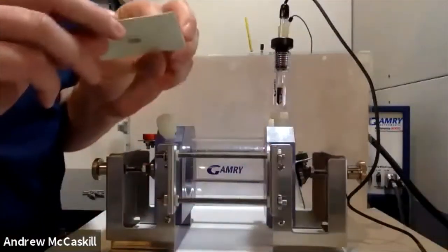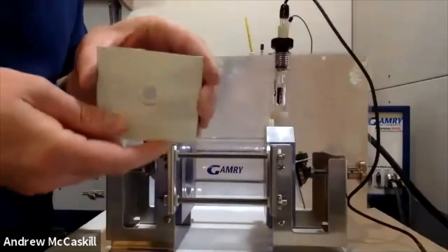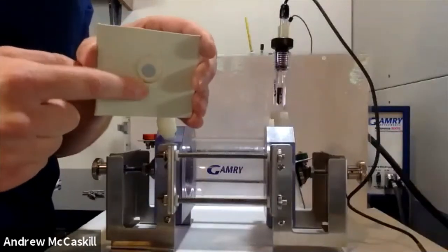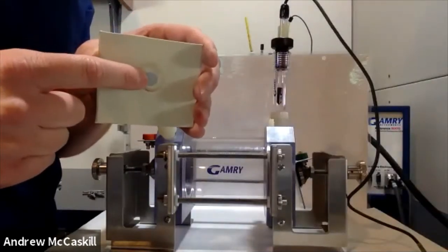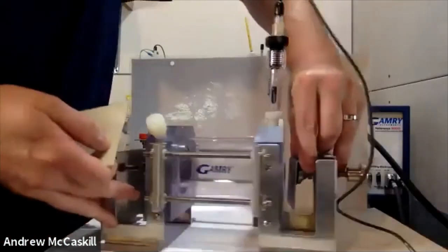So here's just a piece of metal that I have. Also put the sample mask on this. You can see there's where the O-ring made contact, and then I have the exposed area right here on the surface. So you have this parallel plate configuration. You can take samples as thin as what I'm using now, probably a little bit thinner. You can also go out to a sample that's probably just under 2 centimeters in thickness. I'd say it's really close to about 3/4 of an inch is about as thick as you can make it when you unscrew and back up this piece right here.